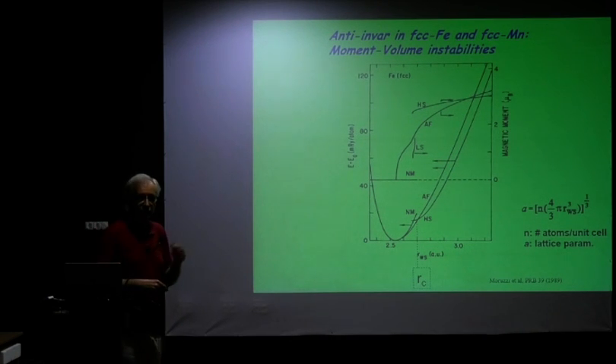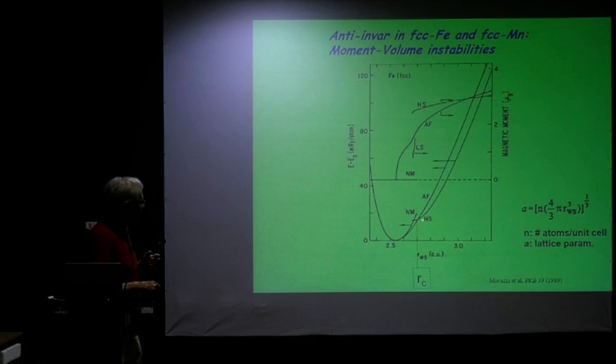And then you redo the calculations for the ferromagnetic state. You find a binding energy curve where the minimum lies at a slightly higher value than the antiferromagnetic state. It crosses the antiferromagnetic state and follows a curve like this, so that you have a critical volume over here, or a critical Wigner-Seitz radius, below which the antiferromagnetic state is the most stable state, and above which the ferromagnetic state is the most stable state.